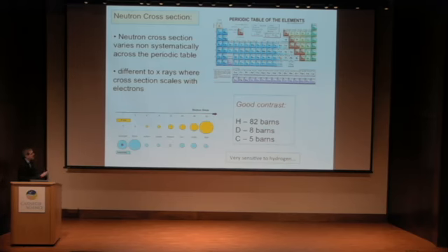But with my current understanding of nuclear interactions, as far as I'm concerned, it varies erratically as you move across the periodic table. A nice illustration of that is this graph down here, which I took from PSI's website, a neutron source in Switzerland. Here they plot the X-ray cross-section as a function of atomic number. You can see it does exactly what you'd expect for electromagnetic interaction. It just grows with the number of electrons. However, neutrons vary kind of erratically throughout the periodic table.